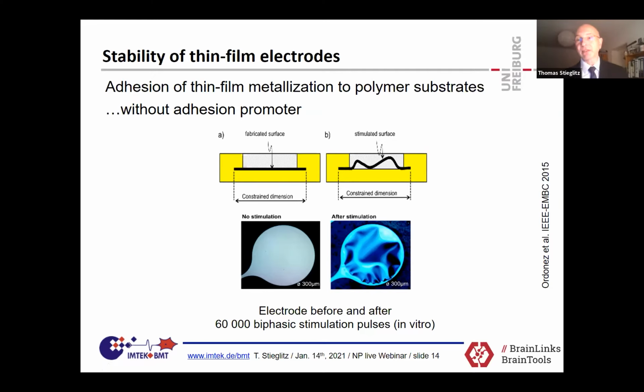And if you have had a metal sheet and a precision mechanics electrode in your hand, you will see it just is there. A thin film is so thin, if you would blow on that and it's not sticking to the substrate, it would just fly away. And that is the challenge here on those slides. On this slide, if you have a really new, pristine thin film, it looks very nice. If you stimulate for about 60, 70,000 pulses, doing nothing, that it really sticks to the underlying ground.